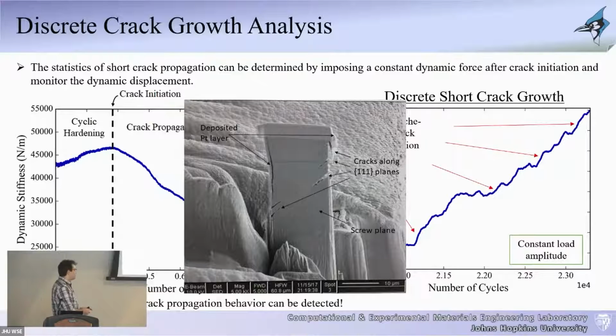Because when we were doing this work, what I was actually interested in is identifying what is happening internally in terms of all these cracks that are nucleating, and how do we actually identify what leads to one of them dominating and eventually leading to fracture. This entire experiment, although it was quite exciting when we were doing it, I realized that at some point it's not really giving us that information. We're really going to the stage where I'm observing a crack on the surface that is the dominant crack, that's the large crack. I'm not able to actually observe the small cracks. As you see, there's a lot of small cracks that actually initiated before that dominant crack formed. So then the question popped up of how do we actually look at that behavior?